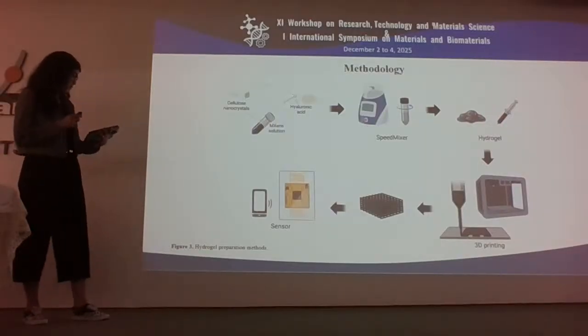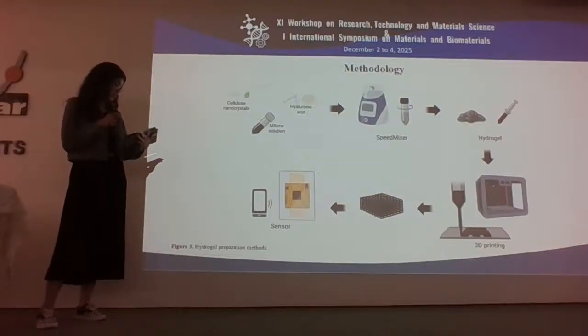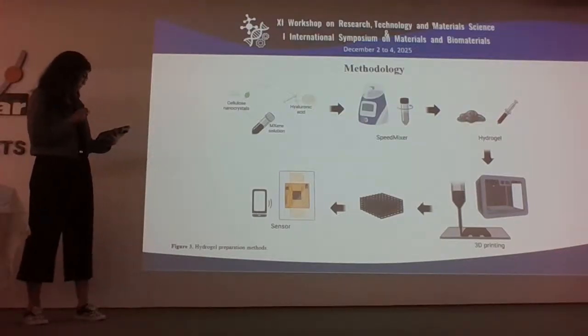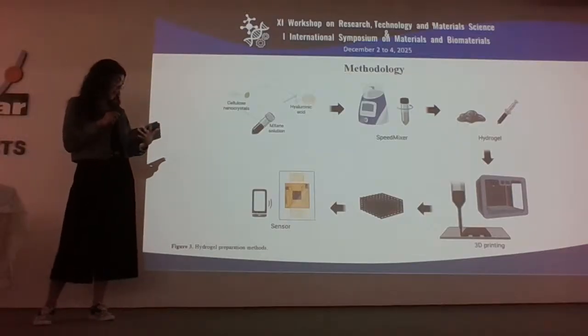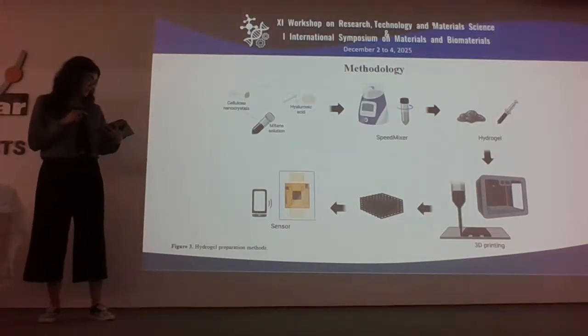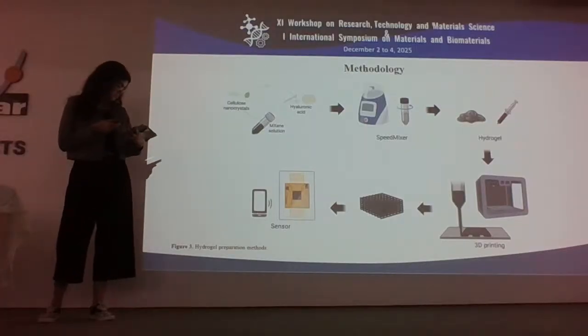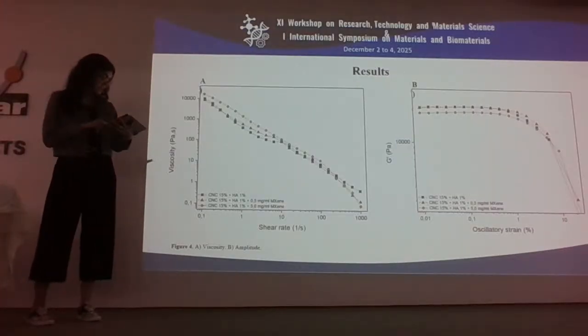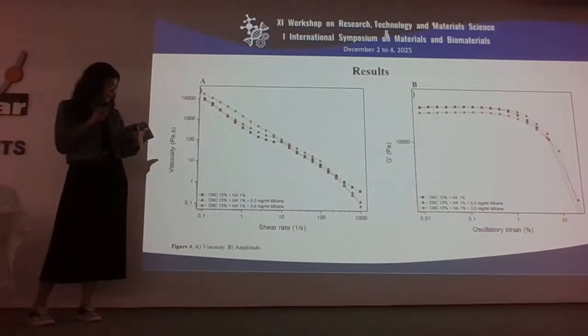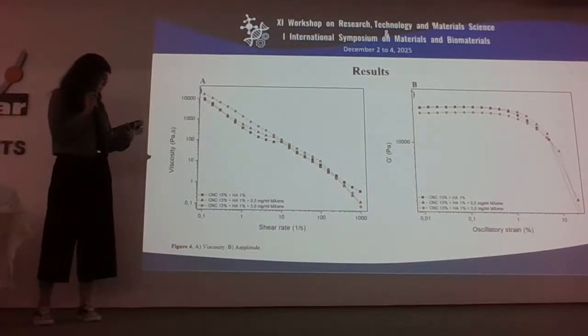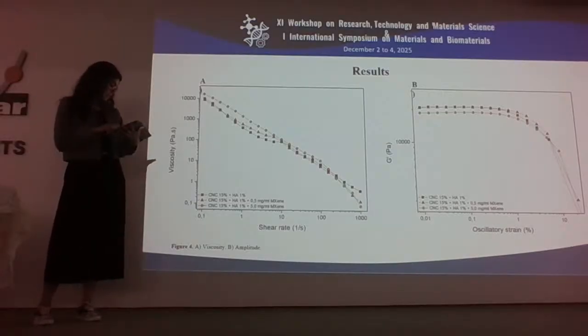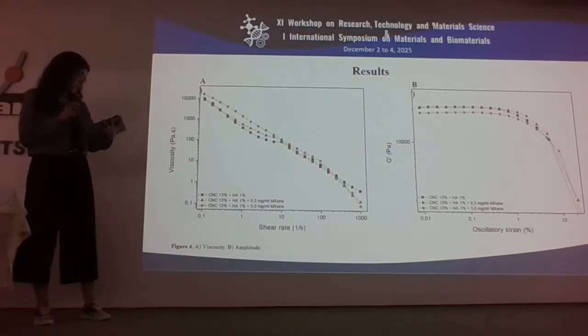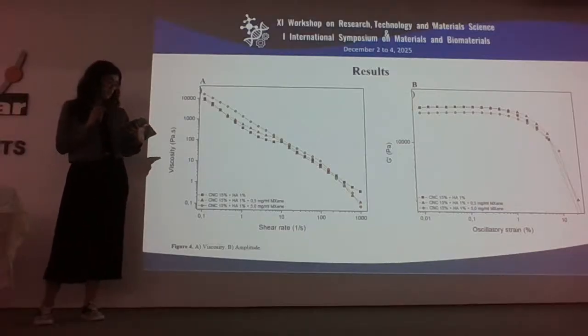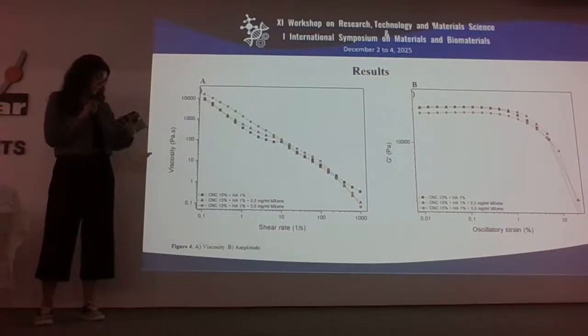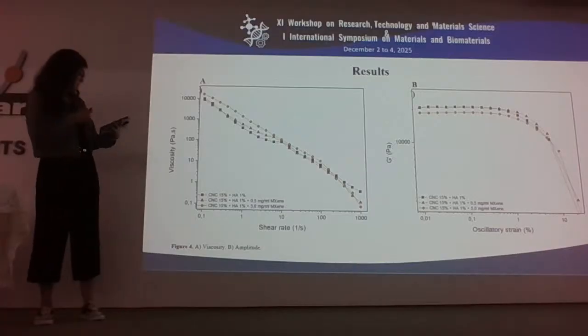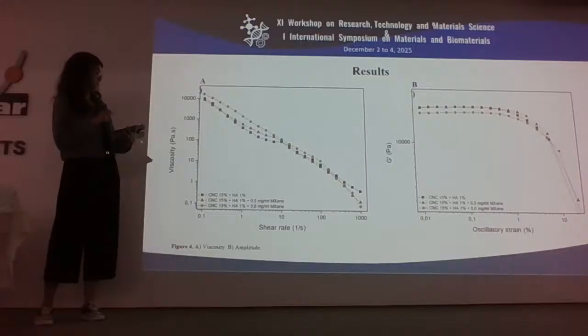To prepare my hydrogel, I used a speed mixer to mix and uniformly disperse the formulation containing the materials in aqueous solution, at both low and high MXene concentration, and then loaded it for the 3D print. In the viscosity tests, we observed that the higher MXene concentration makes the structure stronger and more reinforced. The amplitude sweep analysis showed that the linear viscoelastic region remained stable, indicating that the addition of MXene did not significantly affect the gel.